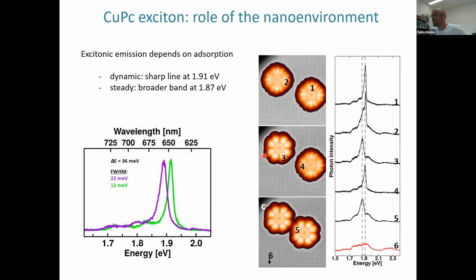When we rescan the image, we see that the molecule switched from dynamic to steady state. And when we do the optical spectrum on this molecule, we see that we only have the redshifted broadband. We can tell that the tip didn't change because we keep the same spectrum on the dynamic molecule, and we can reproduce this on the dynamic molecule by stabilizing it, and again we see the broadband here.